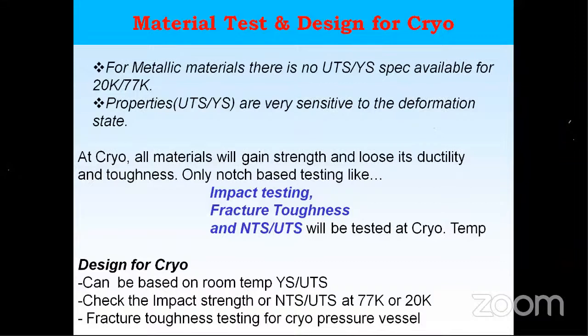So what we do at cryo, all materials gain strength and lose ductility and toughness. So I give more importance to the toughness testing, that is impact testing, fracture toughness, NTS, that is notch tensile testing. This ratio should be more than 1.1 at cryo temperature. If it is more than 1.1, it is safe. The modern way of testing is to do a fracture toughness test and evaluate the value. Based on that evaluated value, the stress available for that particular crack can be used for our application. But mostly the easiest way is to do an impact test.